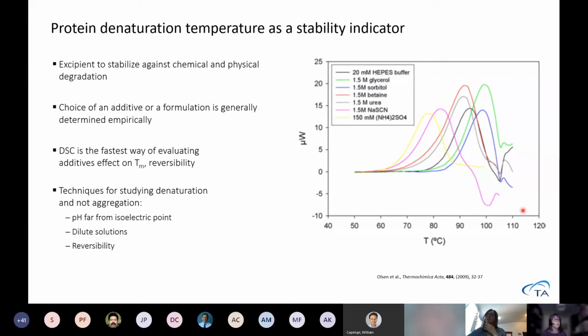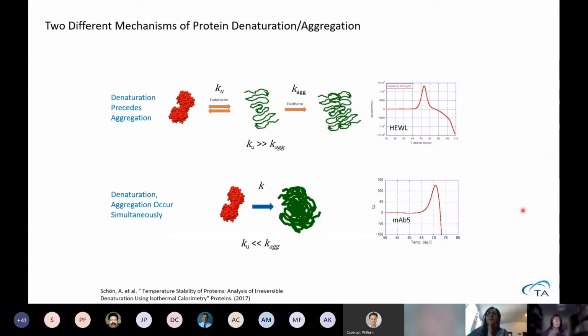So we change the conditions. The higher the concentration, the more prone they are to aggregate. We can look at two different mechanisms of protein denaturation or aggregation, that you can have a native molecule, it denatures and then it aggregates. If you run that in the DSC, you will see first the denaturation peak and then you have aggregation.